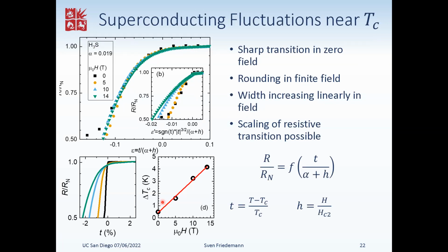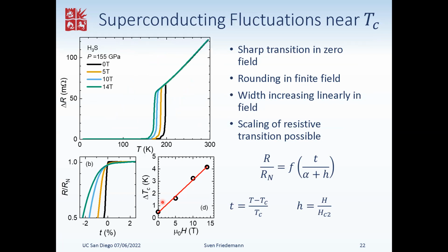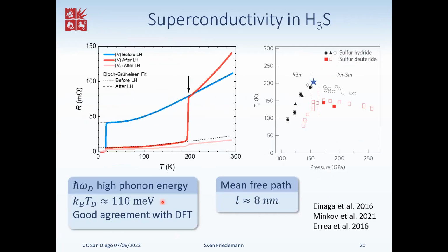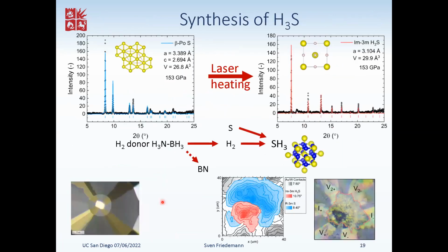Yeah. So one question is, are these multiple domains or a single crystal? Can you say that? And the same question actually, is there a notion of which direction the field points? It's polycrystalline, and this X-ray pattern in particular is fit with a Rietveld refinement, which assumes a powder sample with zero texture, and it's quite a good fit.